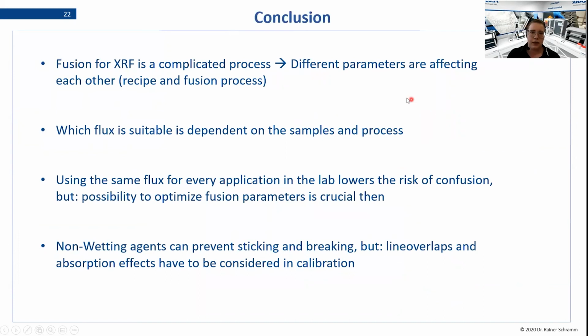So we almost reached the end. So let's have a look on what we just talked about. Fusion is a complicated process, and we saw that a lot of different parameters are affecting each other, and you always have to have a look at the recipe and the fusion process. And then this leads to the next point, which is: which flux is suitable is dependent on both your sample and the process. So you always have to have a look on both.